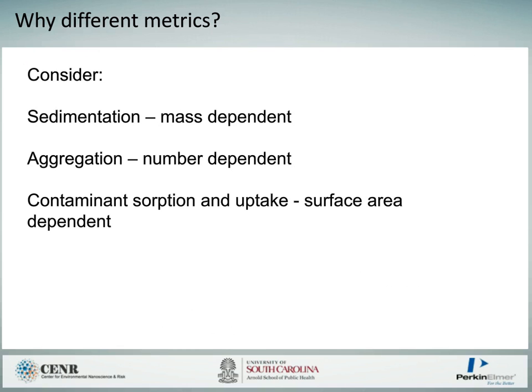When we look at these different metrics, it's often assumed by the community that number and surface area are particularly important and relevant to nanoscience and nanotoxicology. But that's not always the case because different processes which are relevant are dependent on different metrics. For instance, sedimentation may be mass-dependent, aggregation may be number-dependent, and contaminant absorption and uptake, so the absorption of metal or organic contaminants and delivery to an organism, may be surface area-dependent. So all of these different metrics may be important, but for our purposes, the number concentration is quite difficult to measure.